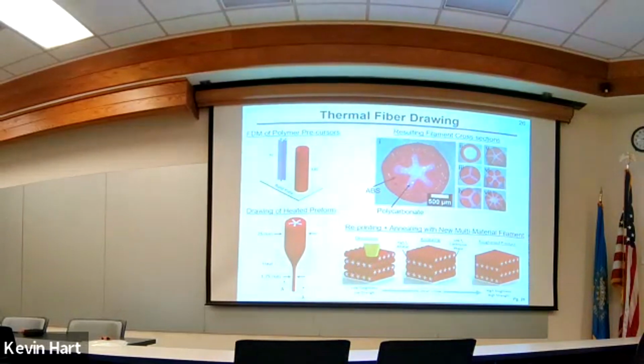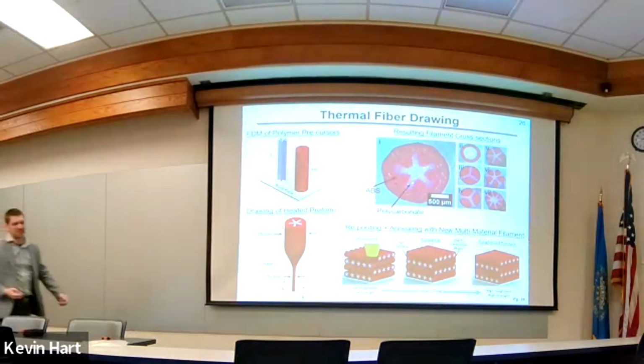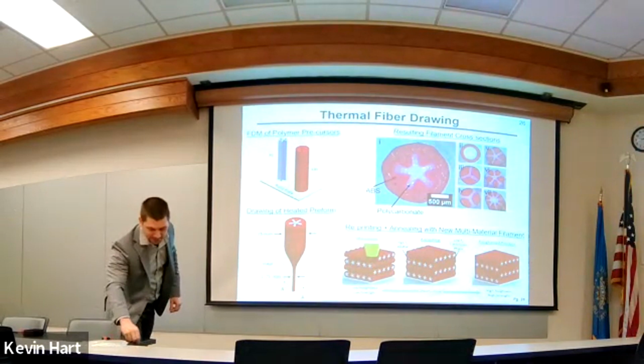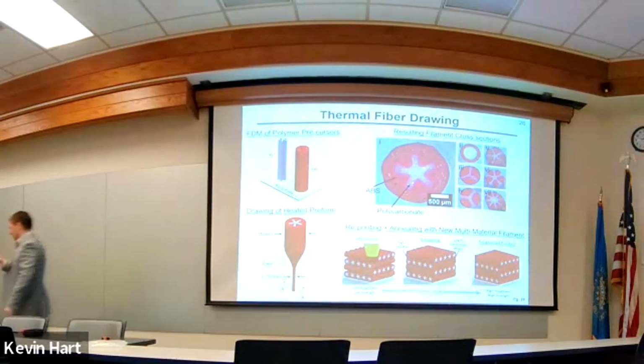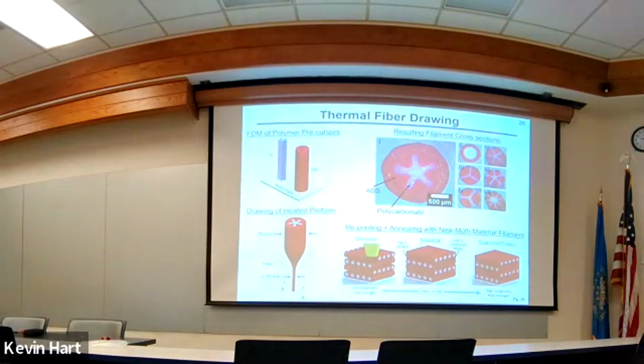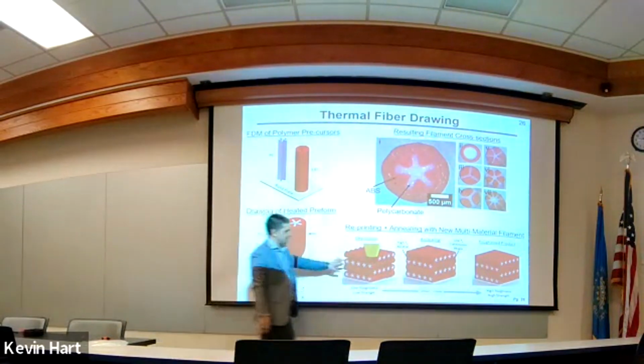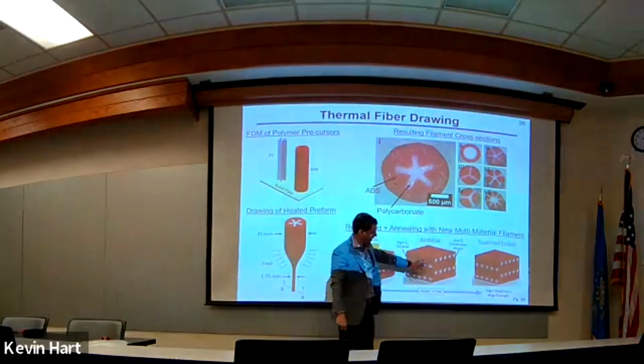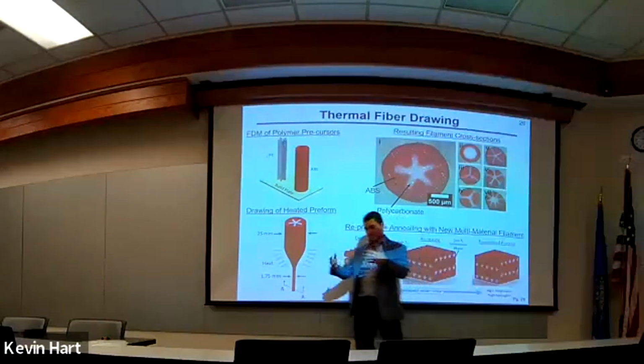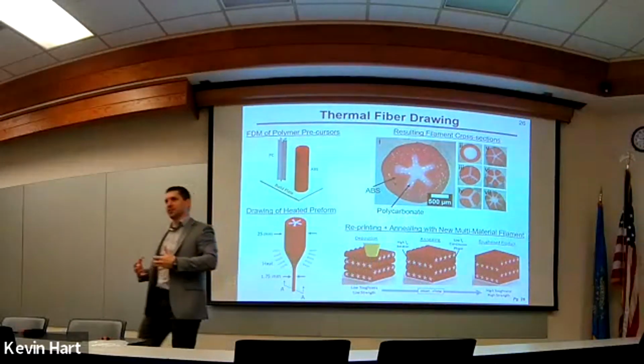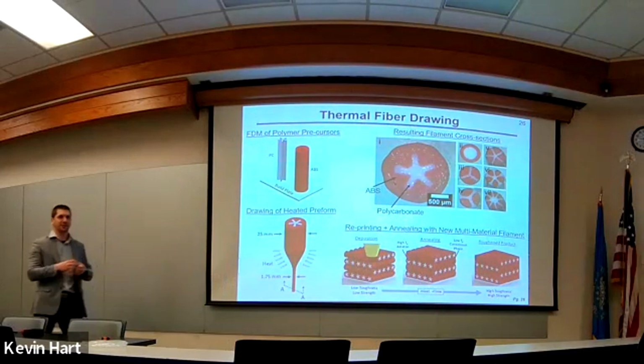Here we go. And I'll also pass around an example where I cut a little bit of the filament. We have spools and spools of this, but test your eyes. See if you can see that star shape in the cross section. So we made this star shape, and now we're going to use that to 3D print a structure. We're going to anneal it, and it's going to weld at the interface, but not lose its geometry because it's got that polycarbonate skeleton inside of there.